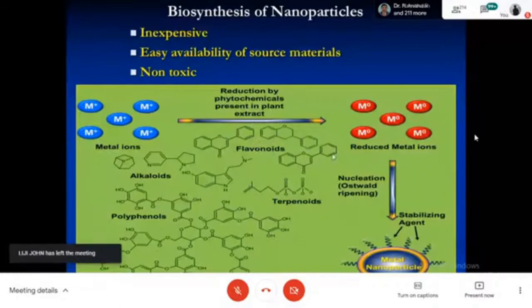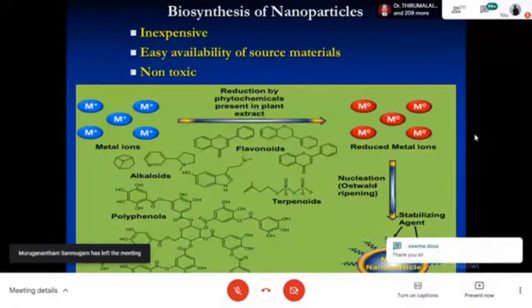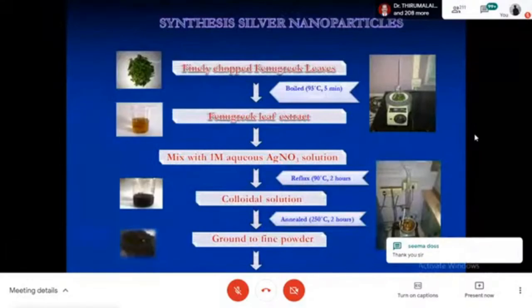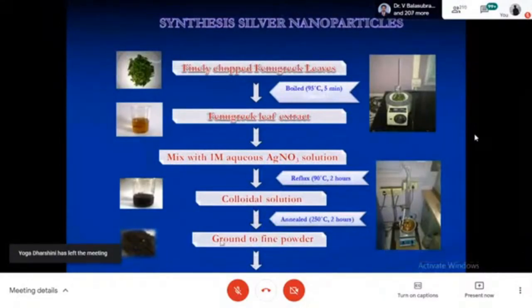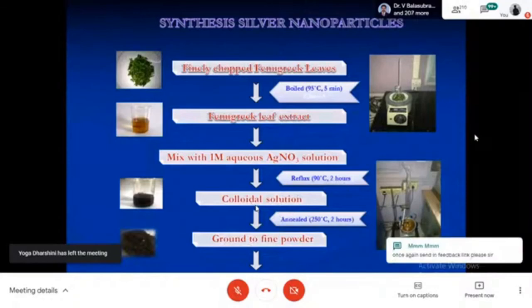So this is actually the plant extract, and plant extract contains a lot of phytochemicals, such as alkaloids or polyphenols. These are all basically very strong reducing agents, and these reducing agents reduce the metal ions into neutral metal atoms, and then it induces the nucleation, then you get the metallic nanoparticles. So this is actually a typical example of how silver nanoparticles are prepared from fenugreek extract.